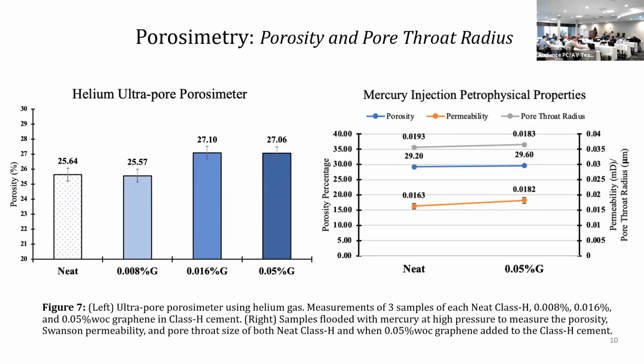We did helium porosimetry for both neat and graphene. There is obviously some error involved with these measurements, but 0.008 was okay. The MIP also didn't really show any major difference in how the pore throats or pore sizes were. Again, I was okay with this, because initially I was disappointed, thinking, but where is this graphene? I wanted to see some evidence of its impact on porosity. But it later became clear that the graphene nanoplatelets do not actually reduce the volume of the pore. They just sit there as very thin plates and provide reinforcement.